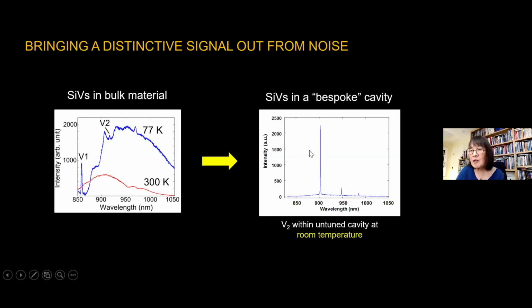When we place the silicon vacancies within this cavity, and we don't do anything to fine-tune the response or the conversation between the cavity and the silicon vacancy, we see immediately, and this is at room temperature, this is untuned, this is the particular V2, you can see that the signal to noise is enormously better. There's an exquisitely thin, narrow response that corresponds to the silicon vacancy within this cavity.